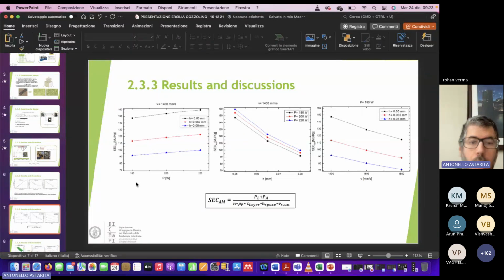Okay. We also tried to correlate the specific energy consumption with the different processing conditions that we varied to evaluate if our formula is good enough to catch the development of the process. And we can say that the formula that is proposed here is good in predicting the experimental results. So as you can see, by increasing the hatch distance, you reduce the specific energy consumption. By increasing the velocity, you also reduce the specific energy consumption. And by increasing the power of the laser, you increase the specific energy consumption.